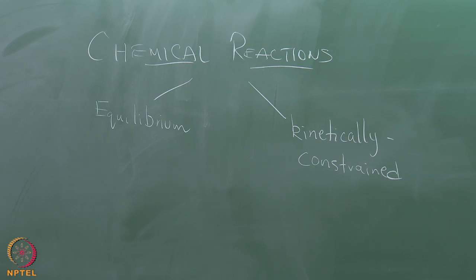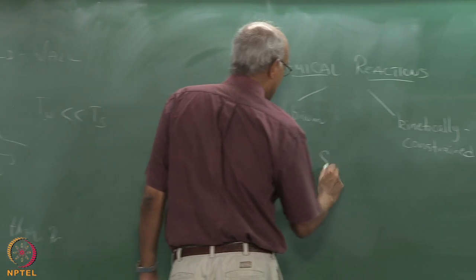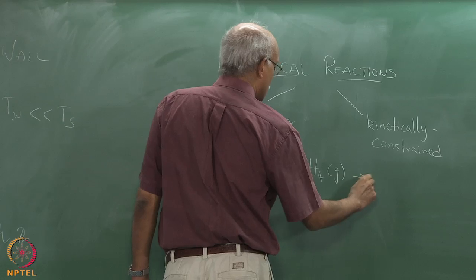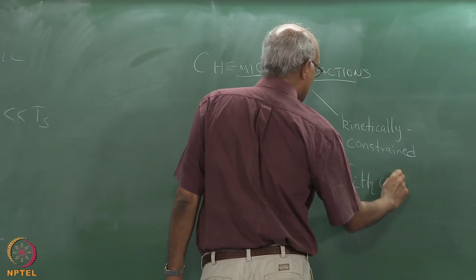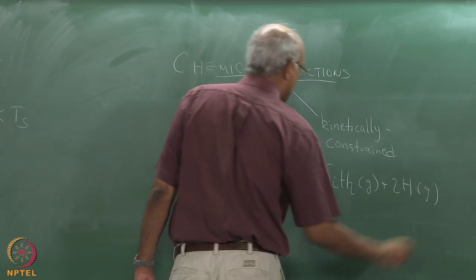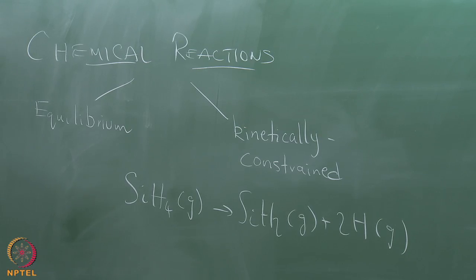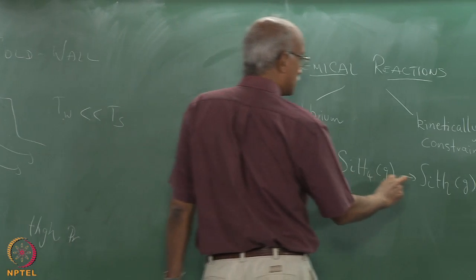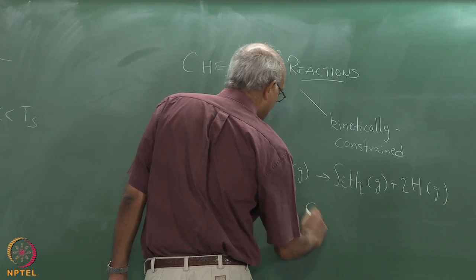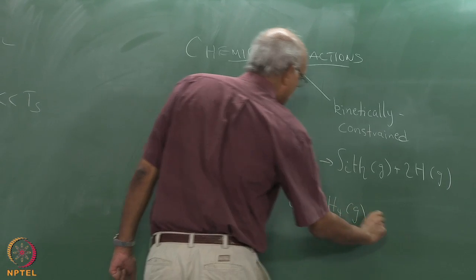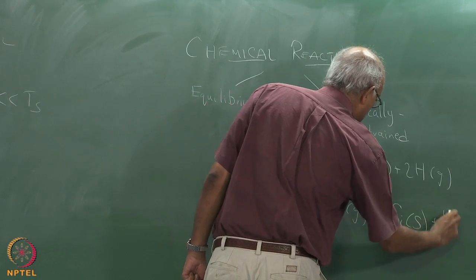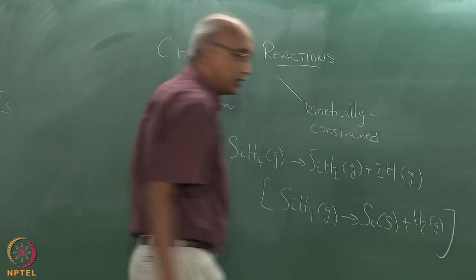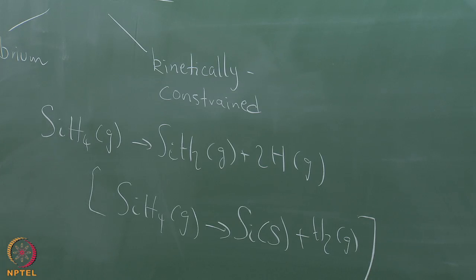So, what that means is if I look at a very simple reaction inside this CVD reactor, where let us say SiH4 gas goes to SiH2 gas plus 2H, which is a typical gas phase reaction that would happen in a pyrolysis CVD reactor, where SiH4 is getting broken down into Si plus 2H2. So, this is only one process step in the overall reaction, which is SiH4 gas going to Si solid plus H2 gas, which is the pyrolysis reaction that I mentioned in the first or second lecture.